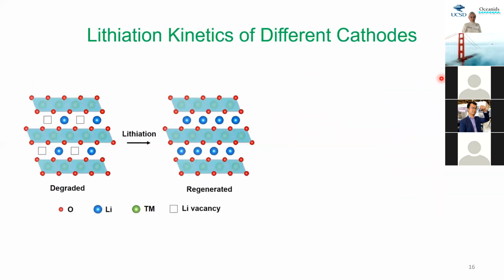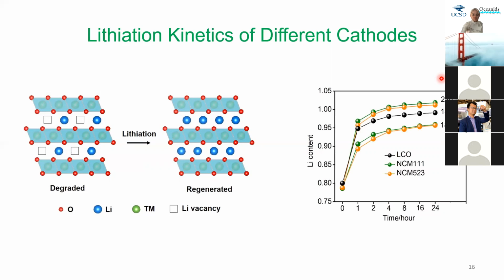I have some data I want to show, but it's probably too much detail. What I want to show here is how to identify the process kinetics and how much time we need to regenerate not only the composition but also the microstructure. So we treated different materials. These are 3 different types of materials. LCO is lithium cobalt oxide. It's probably more popular in cell phones because this material is energy dense, very compact. So we use this mainly for cell phone batteries.